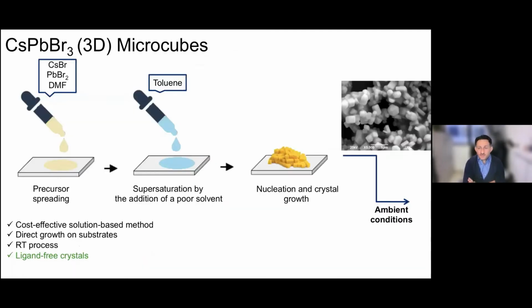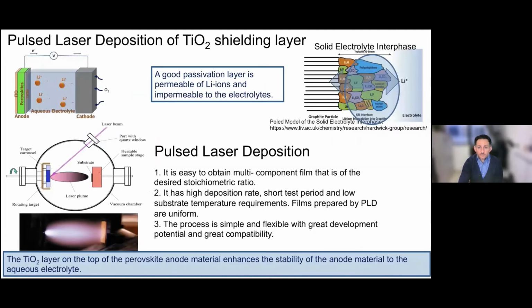And the second one is a three-dimensional structure of nanocrystals. These are microcubes, and they are again very easily formed at room temperature through a cost-effective, solution-based method. You can see here the precursors spreading on the substrate. The formation of these crystals occurs on the substrate itself, and the process is ligand-free. The microcubes we produce are ligand-free, and they nucleate and grow on top of the substrate itself. So we have a direct growth of these microcrystals, microcubes, in ambient conditions.